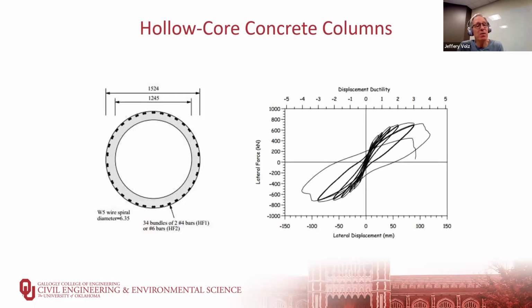And that's because although the bars can't buckle outward because of the lateral tie, you only have the thickness of the concrete, which of course is poor in tension, on the inside, and eventually the bars will buckle inward. So that's why it doesn't have as high a ductility ratio as that square column we looked at.